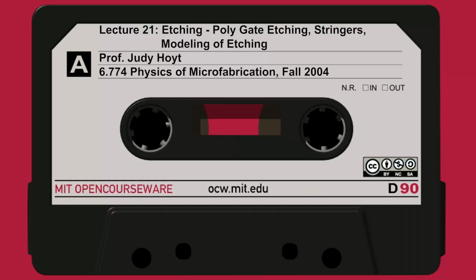What are people doing these days? Well, people these days are not just doing this. For one thing, the gates are a lot narrower. Look at today's gates. Instead of something like 200 nanometers, we're down to 70 or 80 nanometers. So the dimensions have shrunk quite a bit. And people are doing what they call fully silicided gates. So instead of just reacting the polysilicon at the very top of the gate, people are actually putting down enough metal and reacting it at the right temperature that the metal reacts all the way to the very bottom. In this case, the bottom would be nickel silicide.